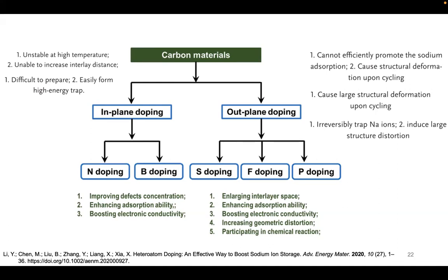While they can add certain improved kinetics, there are some downsides. For sulfur or fluoride or phosphorus doping, you can cause structural deformations that are unintended. And so while you improve kinetics and have faster diffusion rates and subsequent cycling, you introduce more disorder in the breakdown of the material by having these adducts.